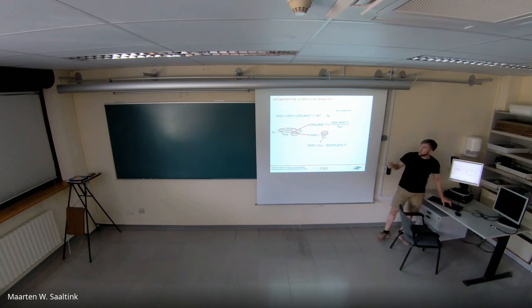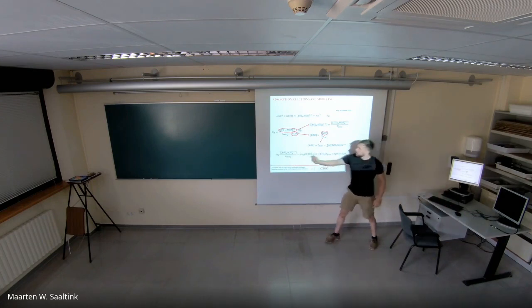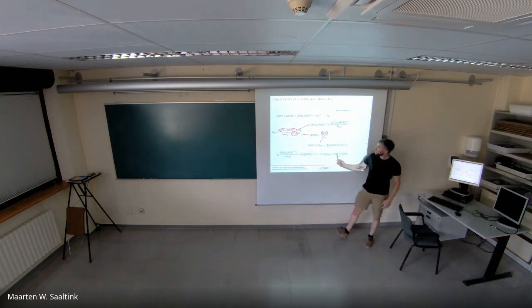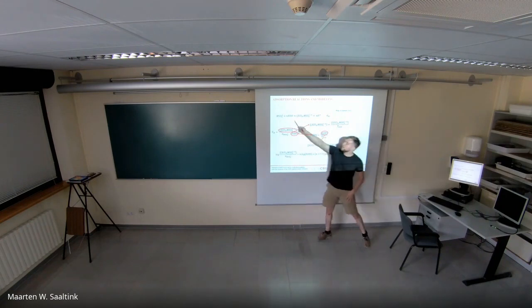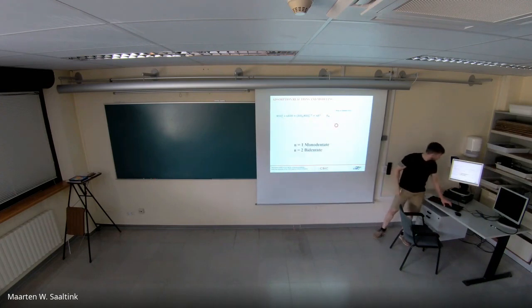So if we apply these changes and express this equation as a logarithm, we can make a linear equation in which n, which is the number of the occupied sites, is the slope of this linear expression.